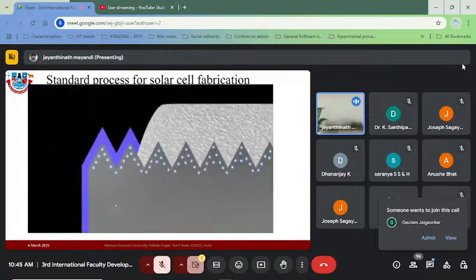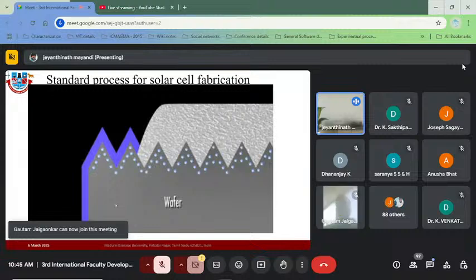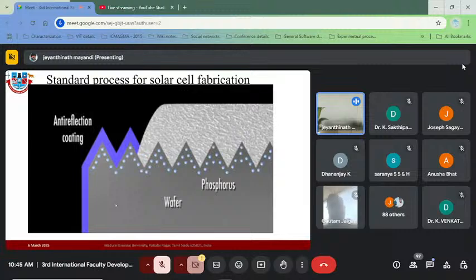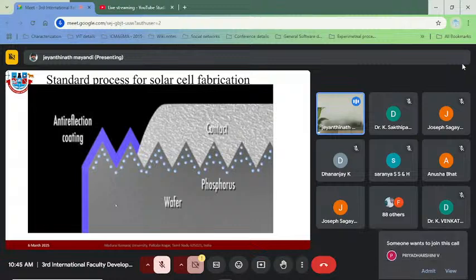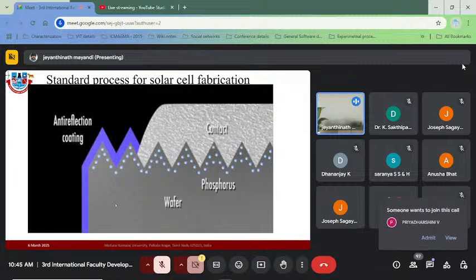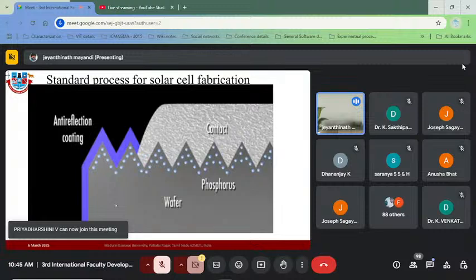This is a schematic of a solar cell. The grey area is the silicon wafer. The surface of the wafer is doped with phosphorus. The blue layer is an anti-reflection coating and covers most of the front surface of the solar cell. But to lead the electrons out of the wafer, a grid of metal contacts is placed on top of the anti-reflection coating. The metal penetrates the coating and contacts the silicon below.